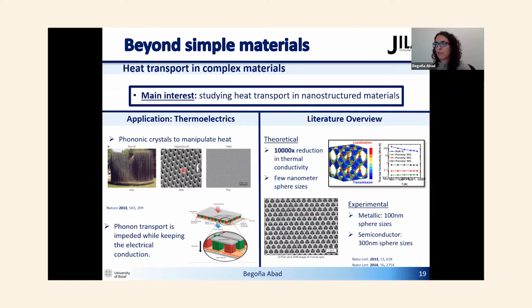So the main motivation here would be thermoelectrics, because the phonon transport would be impeded, but the electrical conduction remains constant. So there are a few works on those types of structures from a theoretical point of view. There are molecular dynamics simulations, and they show a really dramatic reduction in thermal conductivity. But of course, this is for a few nanometers sphere size. On the other hand, there are also some experimental works on metallic metalattices on the order of 100 nanometer sphere size, and semiconductor ones of the order of 300 nanometers.